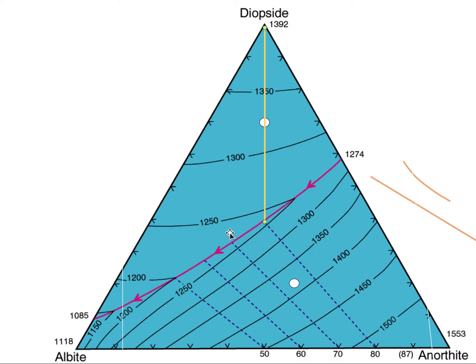Now, what composition and what temperature? Well, in terms of the temperature, here's the 1250 contour here that hits the cotectic and then doubles back and goes in this direction. So we're at a temperature below 1250. Here's the 1200 degree contour. It's not very finely contoured, so we're not going to get a very precise composition, but we'll call it about 1240 just for the sake of discussion. So at about 1240, that's the temperature at which the first plagioclase feldspar will precipitate. What will be the composition of that feldspar? Well, it's going to change depending on the temperature and the liquid composition, and that's what these dashed lines show. So we could follow this dashed line across. You can imagine an infinite number of these dashed lines that connect liquids with their equilibrium feldspar compositions. They won't all necessarily be perfectly parallel to this guy. The liquid will precipitate out a crystal of plagioclase that is 80 percent anorthite.